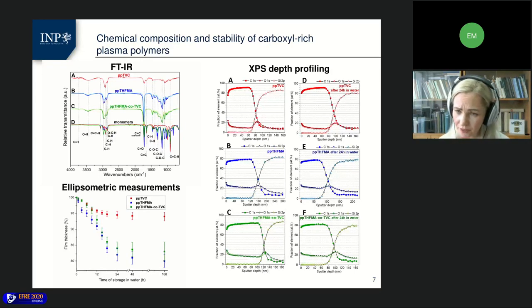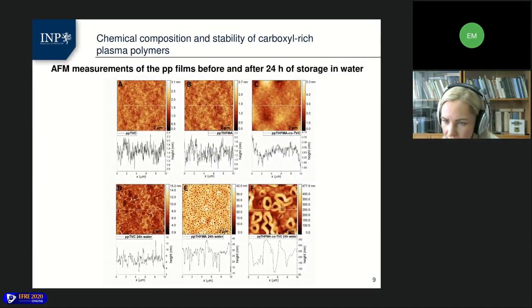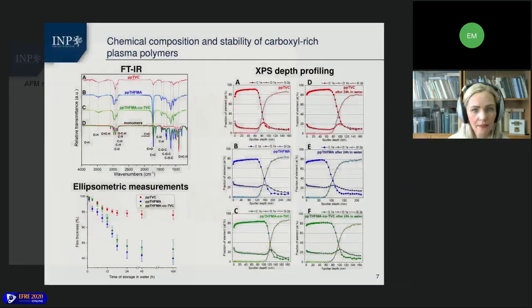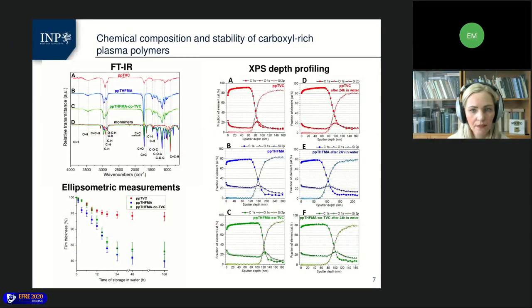Slide 9. Can you find it? Yeah, this is about AFM. AFM doesn't give you chemical composition. You didn't determine chemical composition? Chemical composition was determined by several types of analysis, like FTIR that I was talking about, and XPS depth profiling. So you can see here the summary of all of the chemical groups presented. And then the XPS depth profiling shows the oxygen and carbon content as we are sputtering the material.